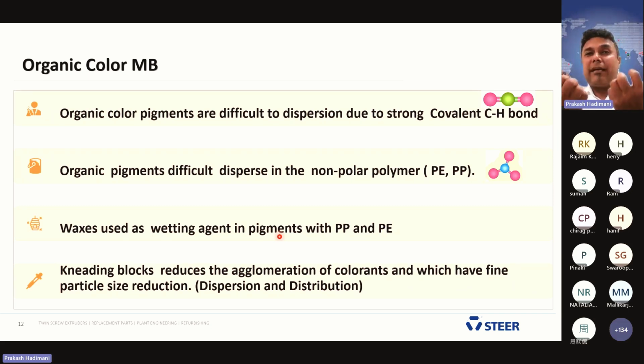So to break the agglomerated particles again, we are using more than 10% of waxes to wet the pigments. And also PP and polyethylene are non-polar. It is not compatible. To mix it, we need to use waxes. It is again an additional cost using the waxes, especially with dry pigments. And to break the dry pigments' agglomerated particles, what is the method to use? There is only one method, use the kneading block to break the particles into smaller and smaller. Then again, you're applying more energy to break the particles. To get dispersion and distribution, you are using kneading blocks to reduce the particle size. It is again a cost.